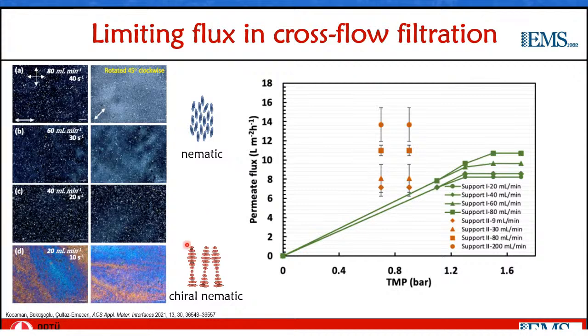crystal materials. At the lowest flow rate, what we see is this multicolor appearance, which is actually typical of chiral nematic liquid crystal phases, where we have aligned planes of these nanorods, but each plane on top of one another is tilted at some angle between consecutive planes.